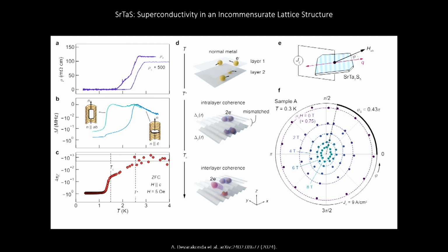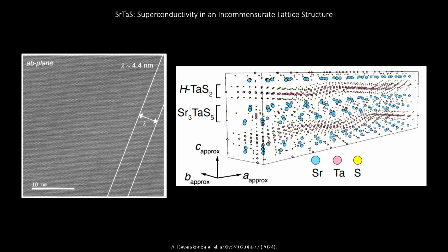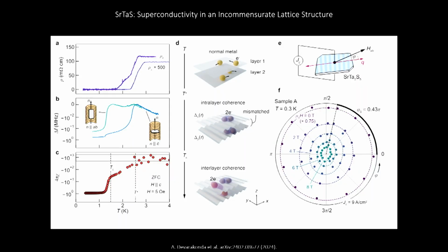The measurements are that we're plotting the critical current, the supercurrent through the plane, so out of plane between layers, as a function of the in-plane rotation angle of the magnetic field. And you can see that because the superconductor has these stripes in its structure, it imprints itself on some anisotropy, this lobe-like or oval-like parameter, that the superconductor is stronger in one direction and weaker in another direction.